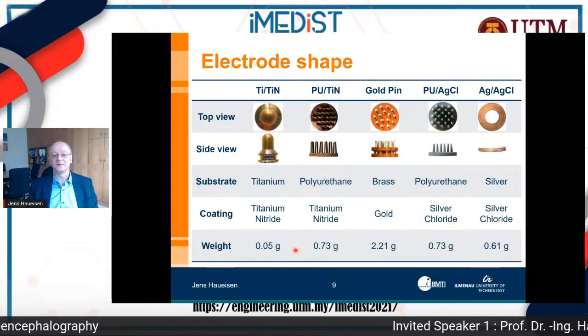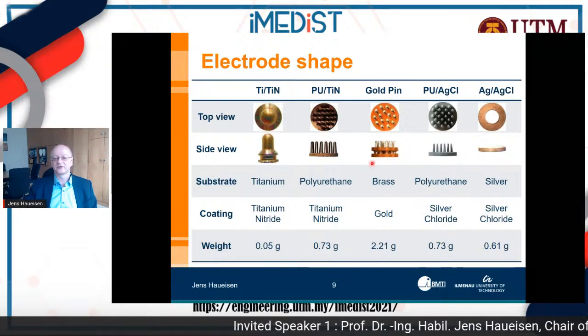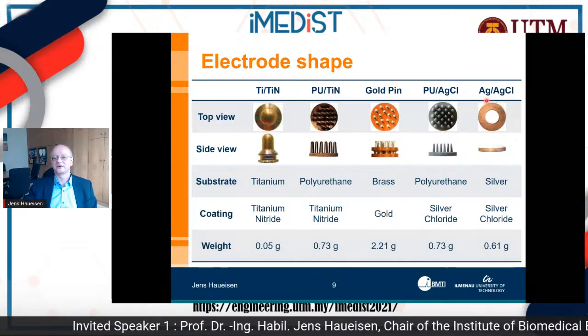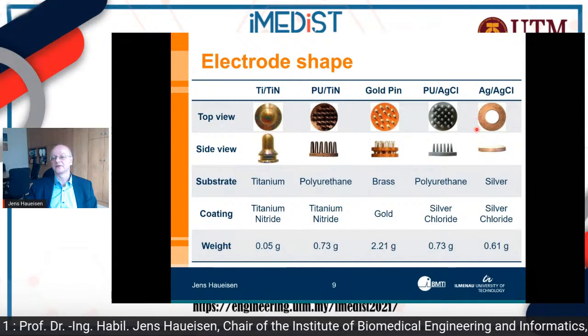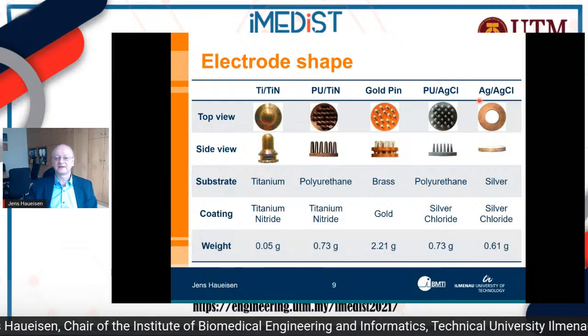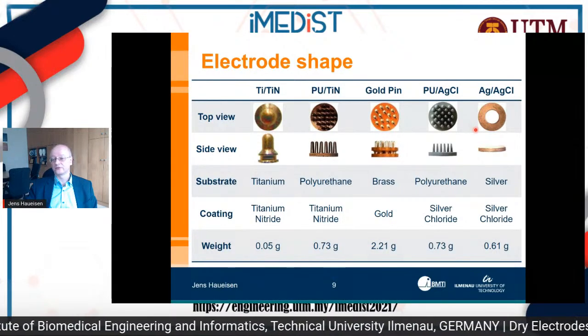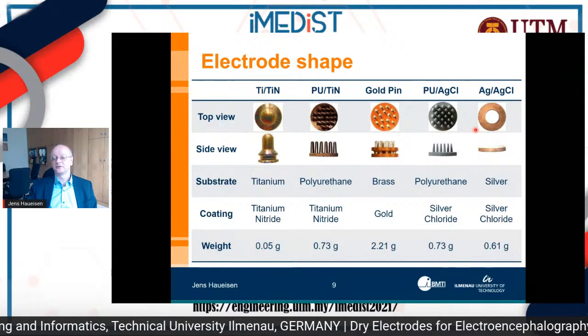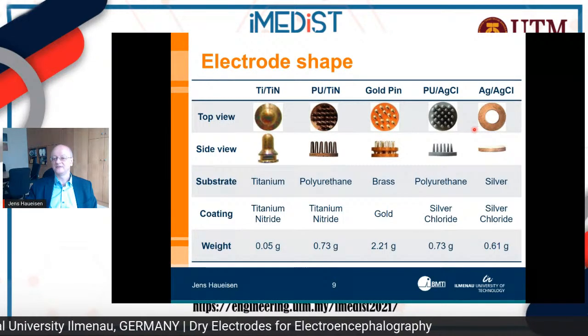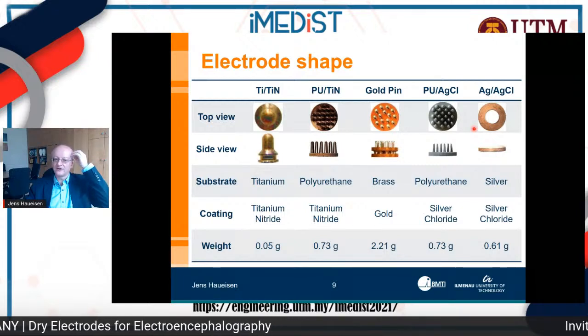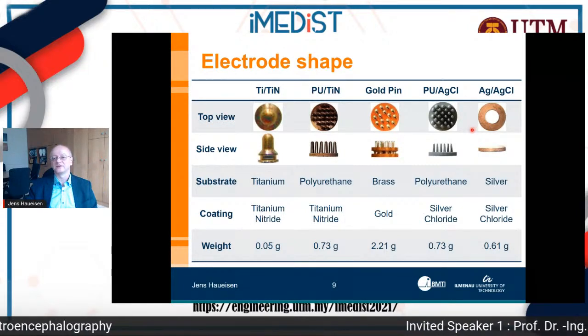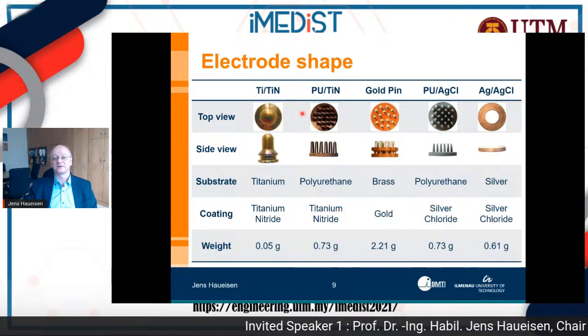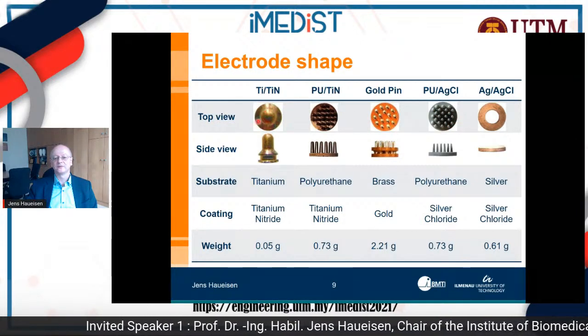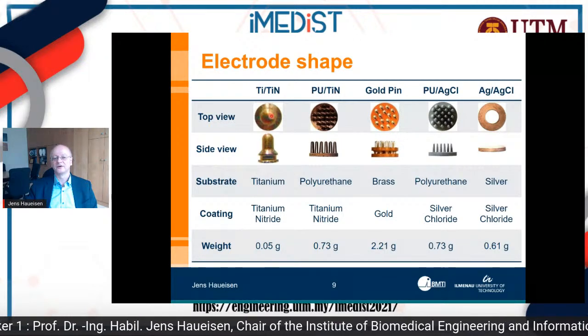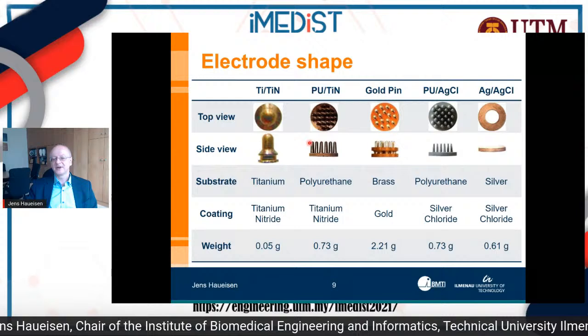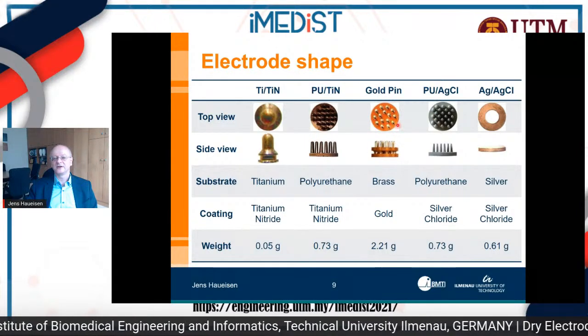So the first thing is with your electrode, the standard electrode, which you see here on the right side, the standard gold or silver chloride electrode, that is something where you need paste to get through the hair layer. However, if you want to have a dry electrode, then you need to go through the hair layer in such a fashion that you can contact the skin without the gel. That means you need to have a pin shape like the ones you see here. Actually, this one is only about 1.5 millimeter in diameter, so it's enlarged here because it's a single pin. And these pins have different shapes, as you can see here, and different sizes.